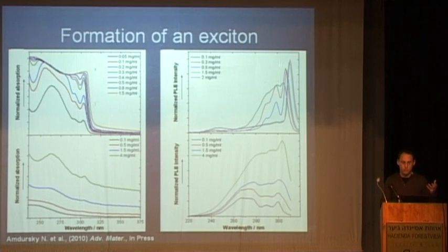However, if we look at the graph of the hydrogel, of the peptide nanotubes formation, we can see the transformation from a broad photoluminescence excitation on the black curve into a very narrow photoluminescence excitation after the gel is formed. The full width at half maximum of this PLE peak is only 4 nanometers and even less than that. So it can tell me that an exciton is formed and also a nanocrystalline is formed, because if it wasn't, I would receive exactly like the bottom curve, a broad photoluminescence excitation. It's almost a discrete excitation level.